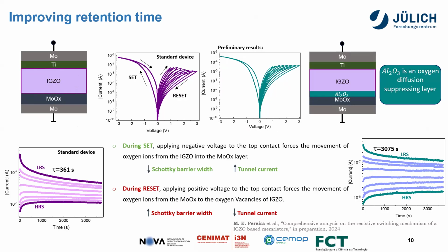So if we want to suppress this charge exchange, based on the papers from Jülich, from the group of Professor Regina Dittmann, we learned that we can apply a small layer of aluminum oxide. This is in collaboration with Jülich. And this way we can, in fact, improve the retention time. It's still not full, so I have the figures of retention time with the tau decay that we did with the fitting here. That is better, of course, in this case.